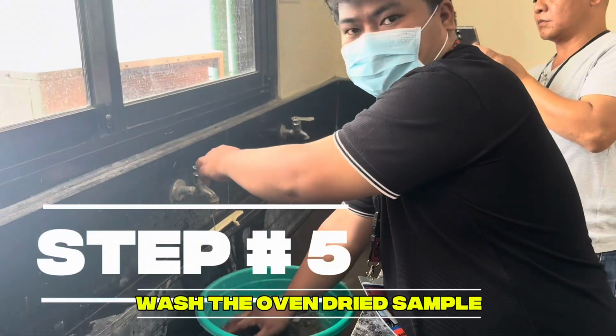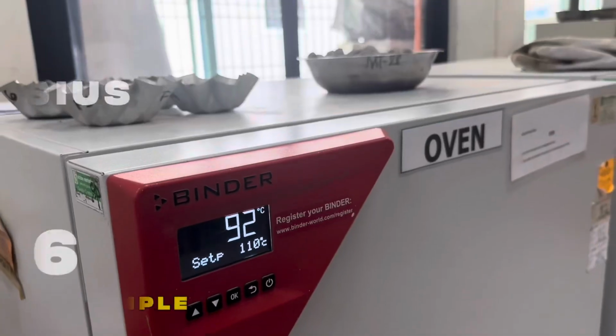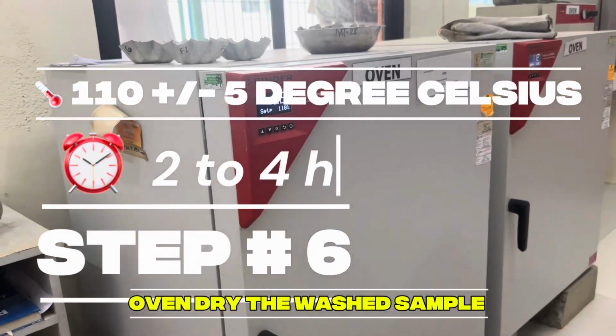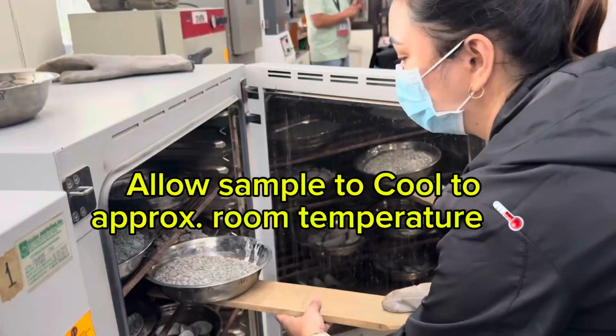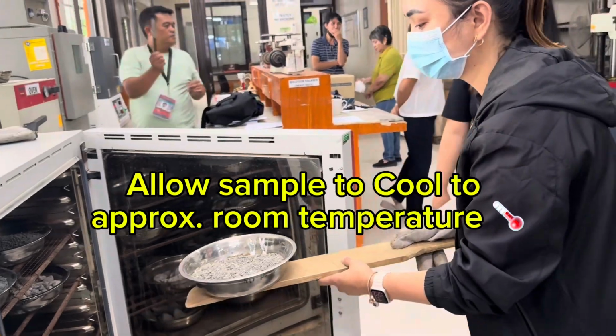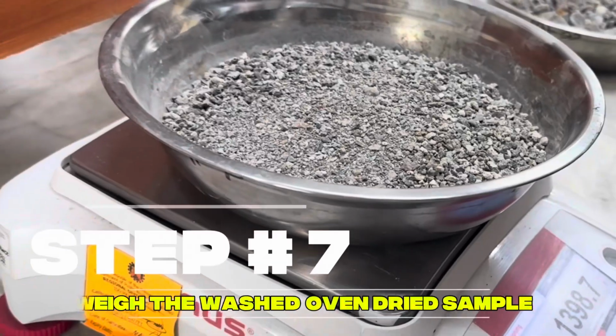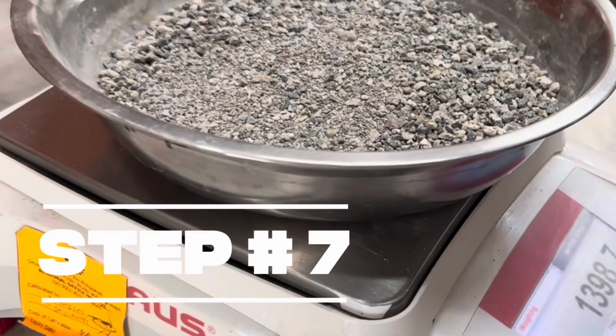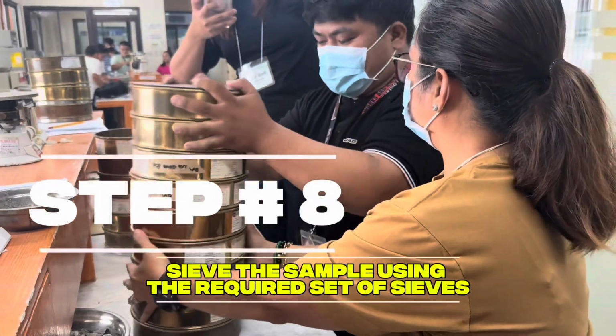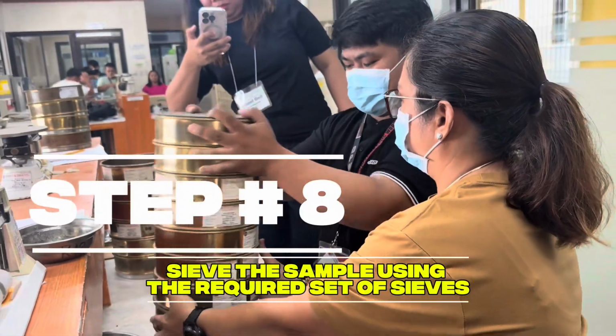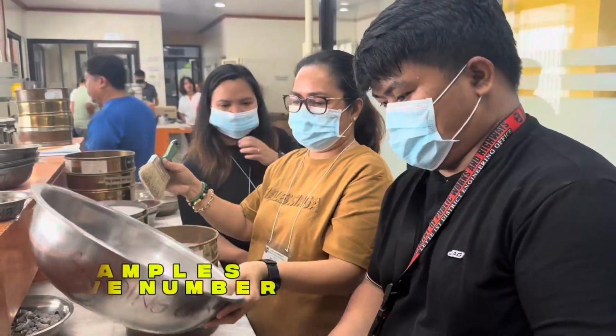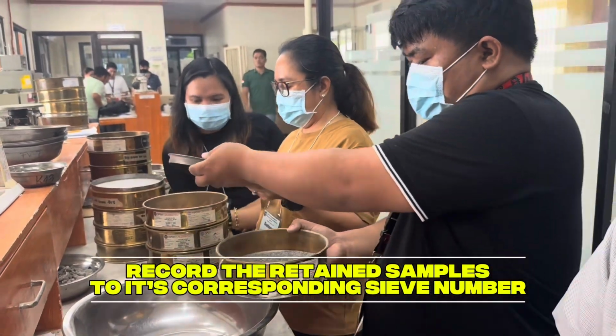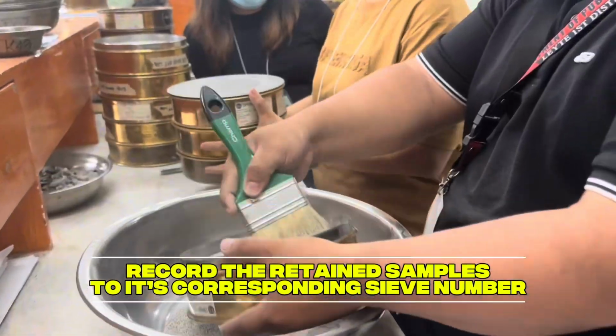Step 5, wash the oven dried sample. Step 6, oven dry the washed sample for another 2 to 4 hours. Then allow the sample to cool to approximate room temperature. Step 7, weigh the washed oven dried sample. Then at step number 8, we begin sieving the sample using the required set of sieves. At this time, we record the retained samples to its corresponding sieve numbers.